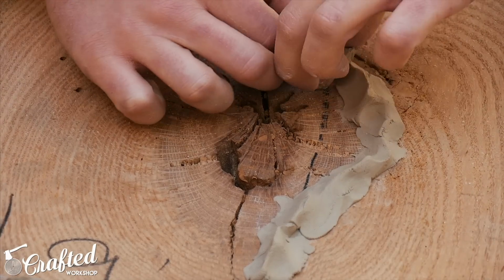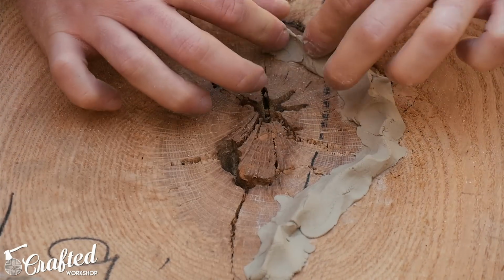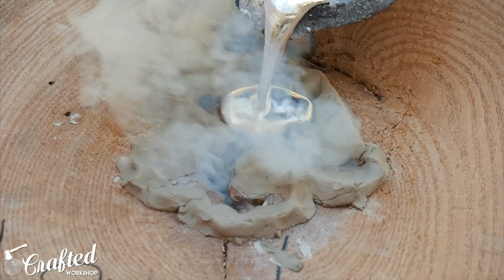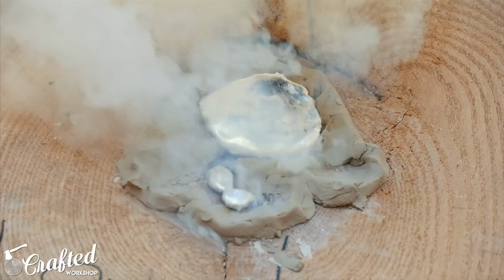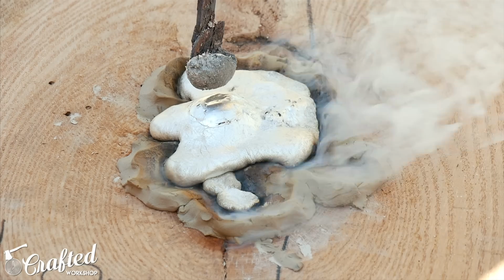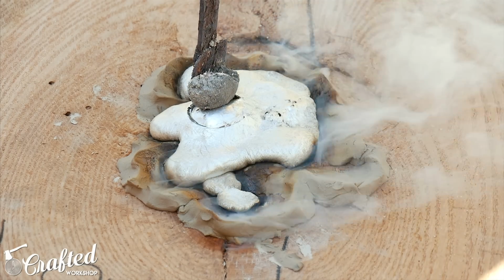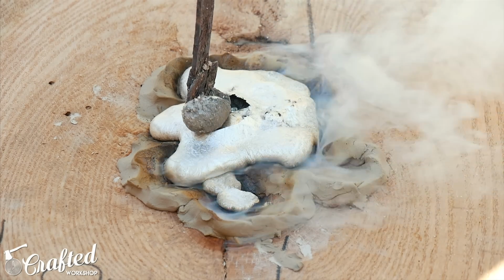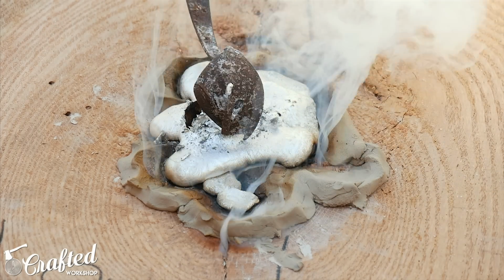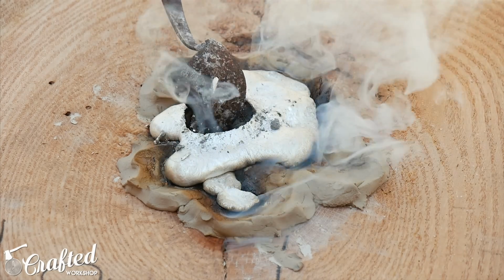Now, there was another void in the slab, but this one didn't go all the way through, so we prepped the top of the slab with more clay and poured some more aluminum. This one didn't go as well. We actually had a big air bubble in the pour, and it was also above the surface of the slab about 3/4 of an inch, so there was a ton more cleanup to do on that one, but it still ended up looking pretty nice.